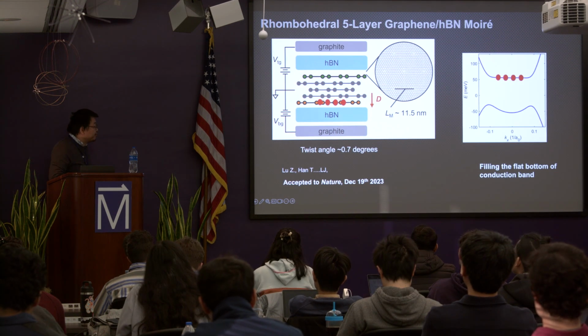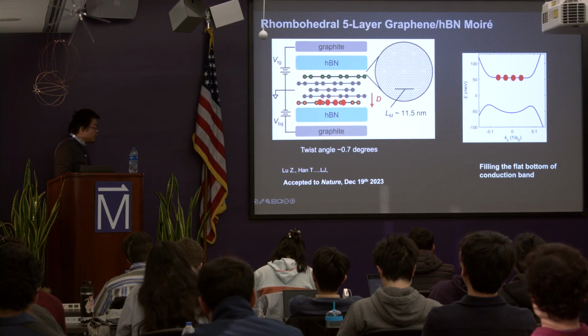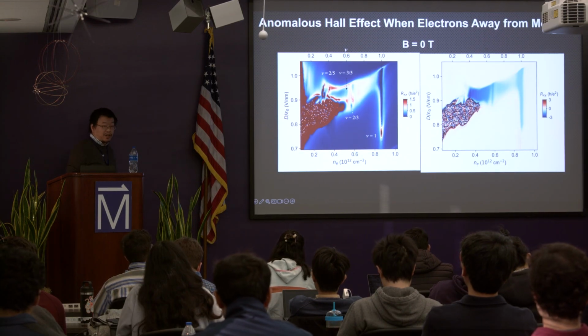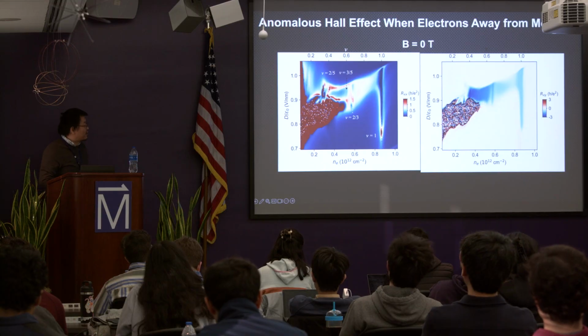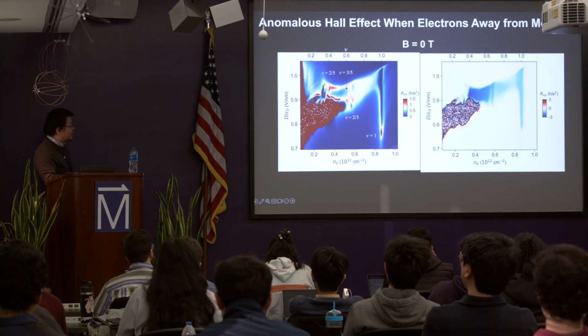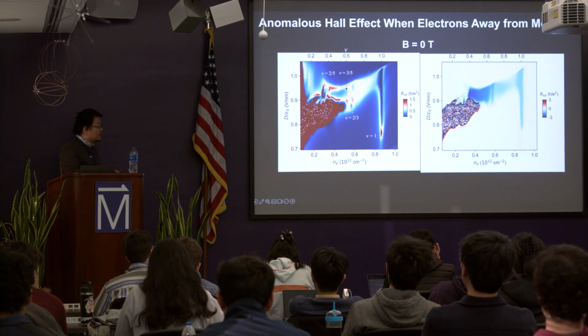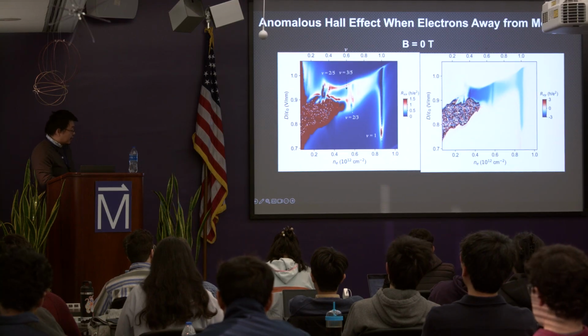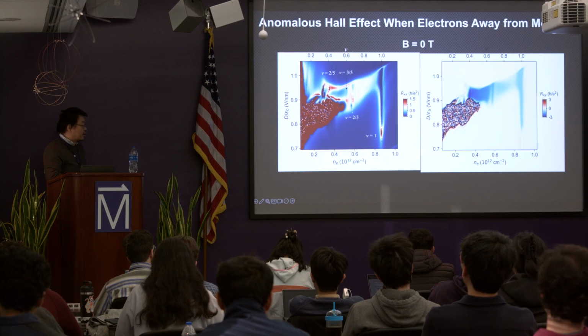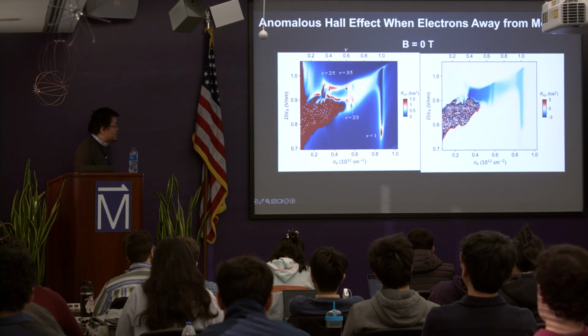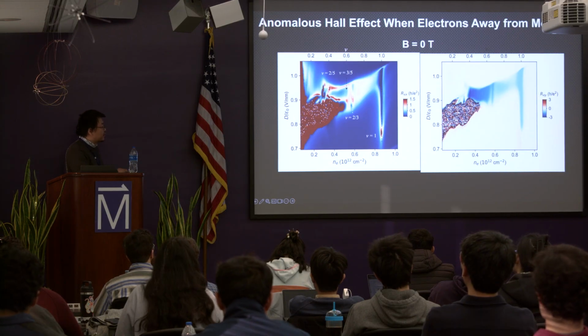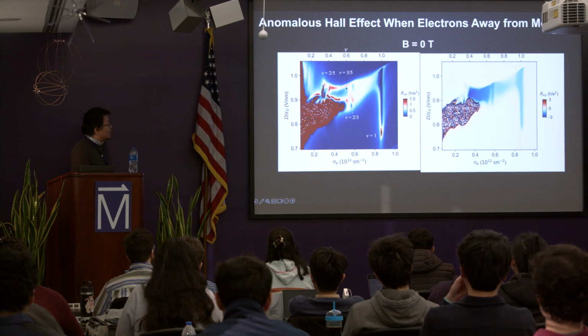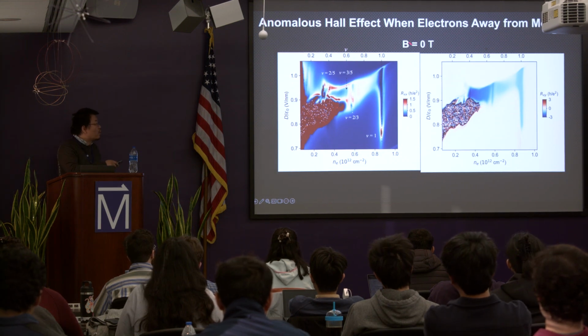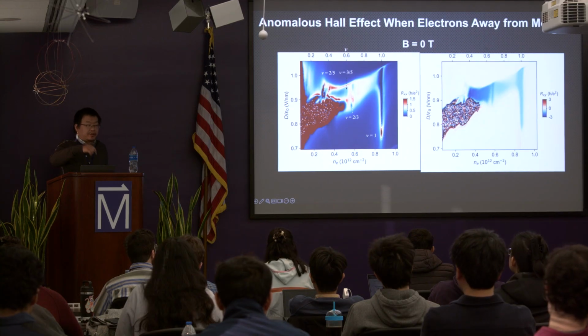So with this setting, we make the Hall-bar device, and you measure transport, Rxx and Rxy. On the left side is the longitudinal resistance, and on the right side is the Hall resistance. Again, the horizontal axis is the charge doping, the charge you dope into it, and the vertical axis is the electric field. You can also convert it into the filling factor. Filling factor 1 means I have 1 electron per moire site.